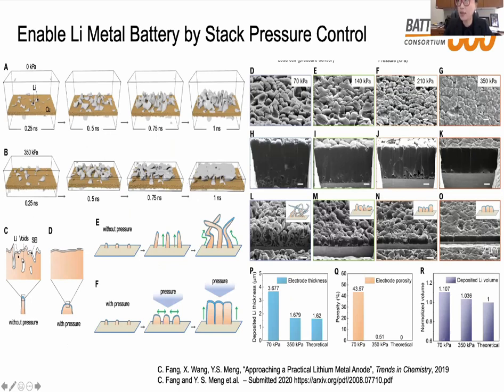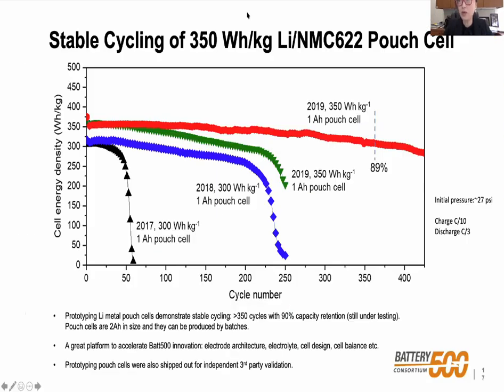And then you can see the lithium deposit. These are 2 micron scale bars, right? So we're depositing very thick lithium, and you can see almost perfect columnar structures of the lithium can be deposited reversibly, right? The most important part is how you can strip those lithium and deposit it back. So I think through this exercise, pressure control becomes such an important parameter. So it's implemented in the pouch cell development.